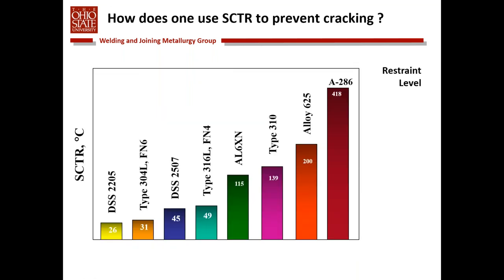How do we use this data? If we look at some of these values now in a chart, and we look at restraint level. If the restraint level is low, you might determine that only materials with an SCTR over maybe 200 degrees C are susceptible. As the restraint level increases to medium and high levels, the critical SCTR value above which materials are susceptible to solidification cracking is what is shown above the dotted line here. So some of the materials down on this end of the spectrum, some duplex stainless steels, 304L, 316L that solidify as ferrite, we know are very, very resistant to solidification cracking, and that is recognized and verified by their SCTR value.